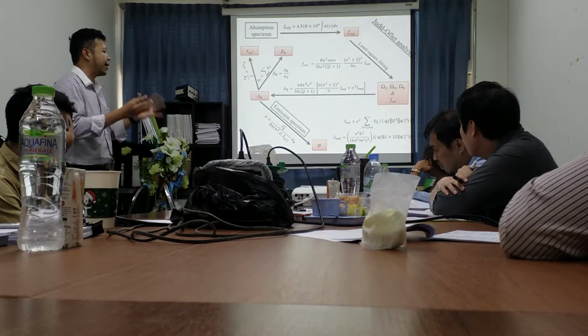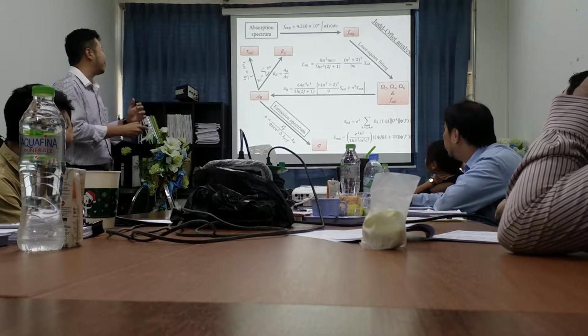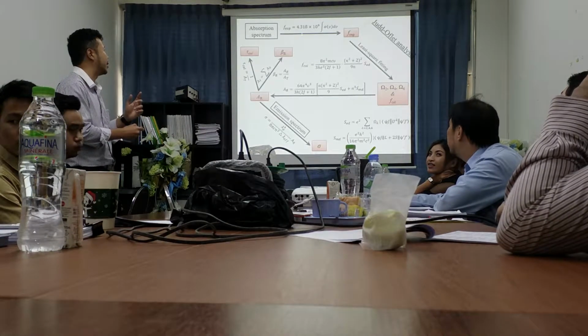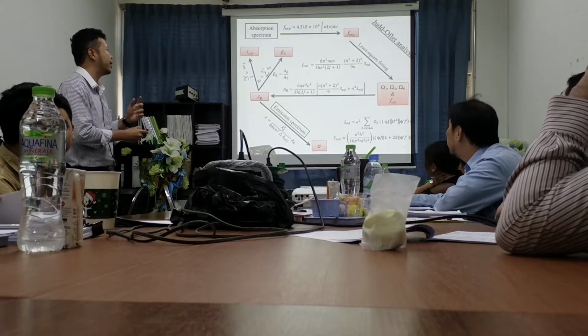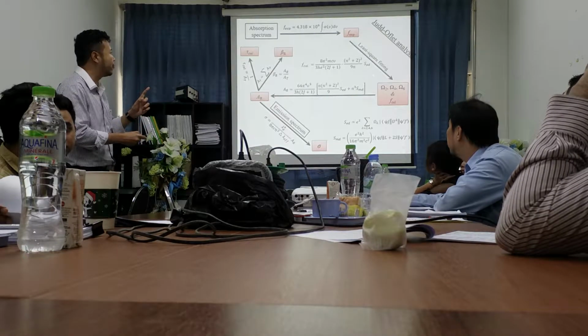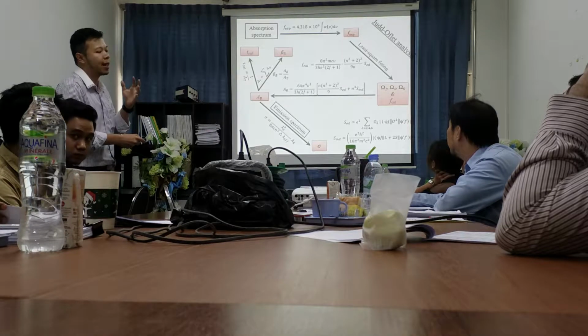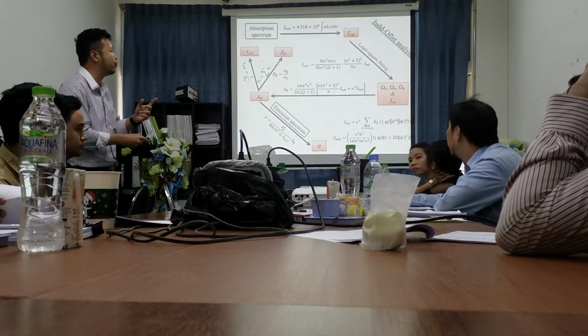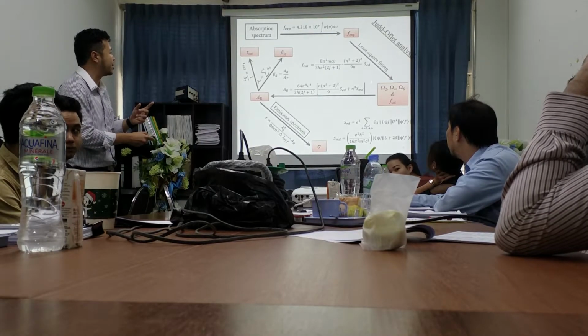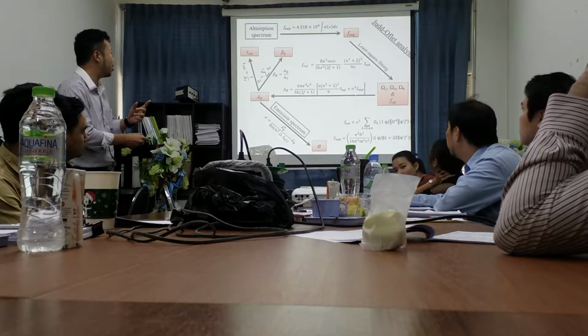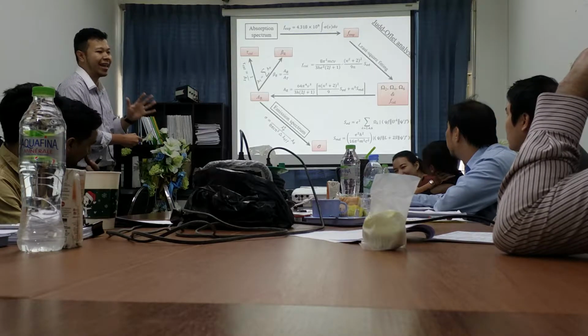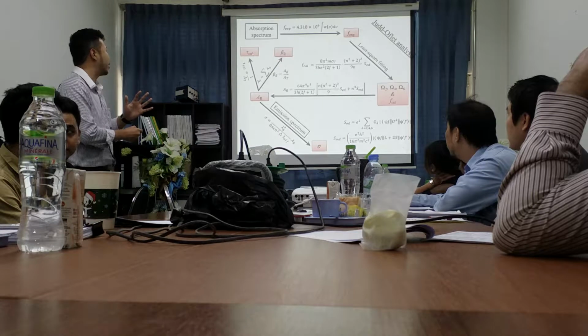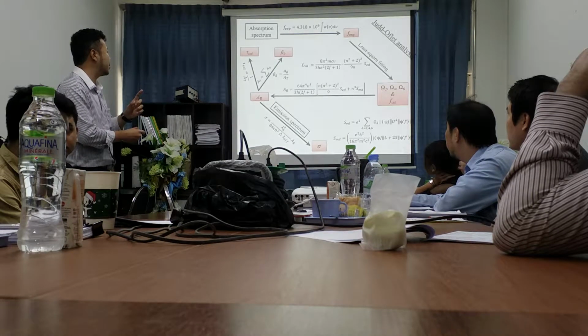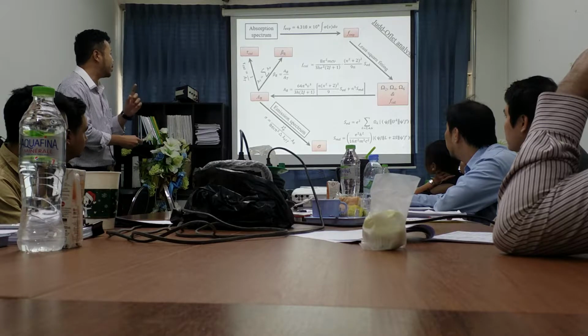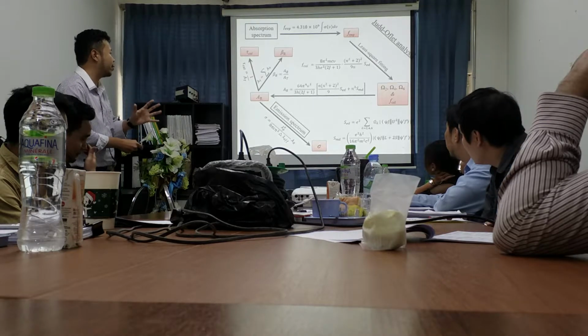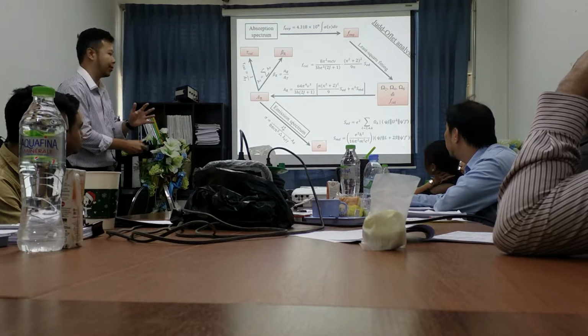This is the diagram of the Judd-Ofelt analysis. We start by using the absorption spectrum to calculate the experimental oscillator strength (f_exp), and then we use f_exp to fit with this equation to get the calculated oscillator strength f_cal and the Omega 2, 4, and 6. Then Omega 2, 4, and 6 are put into this equation to find the radiative transition probability A_R, and A_R was used to evaluate the calculated lifetime tau_cal and branching ratio, and finally we take these values with the emission spectrum data to get the final value sigma, the stimulated emission cross section.